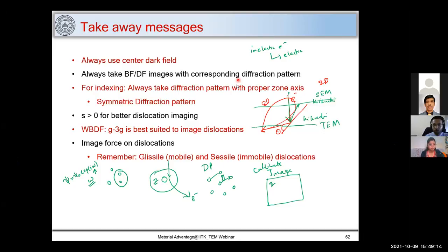And one more important thing: when you tilt your sample, do not focus your sample electronically. What do I mean by that? There is a knob, and you try to focus with it. Basically, you are disturbing the alignment, and the dislocation also will start moving. So what you do is adjust the height. You move your sample in eucentric height. You use the Z height and try to adjust the focus, or try to focus the image.